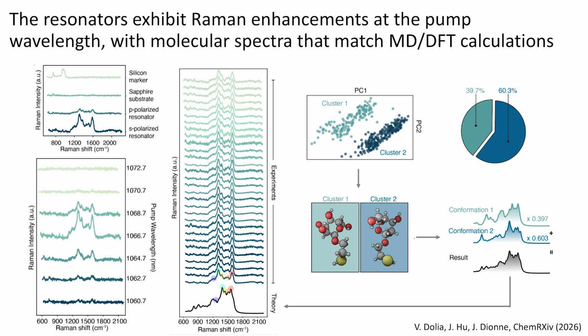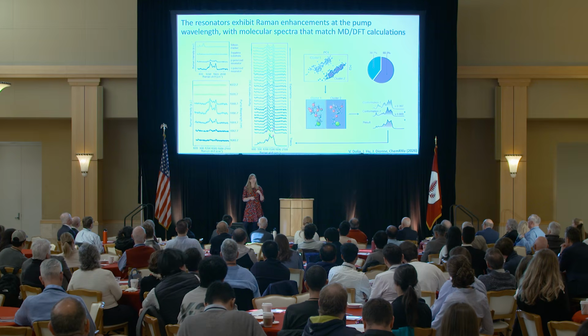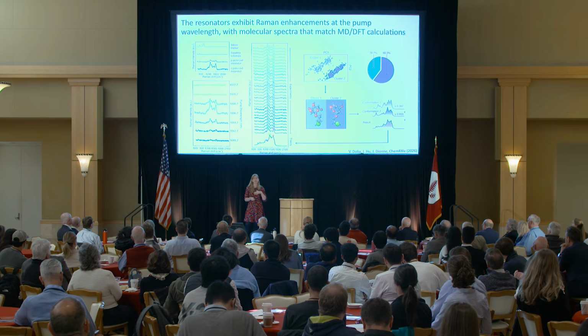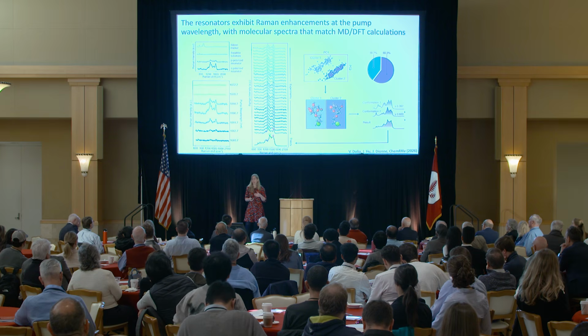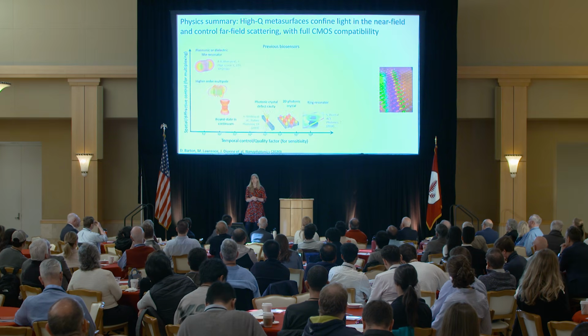And then, based on the Raman spectra and the amount of time that the molecule spends in different conformations, we're integrating for on the order of tens of milliseconds, up to about a second. We can take weighted averages of the Raman spectra based on how long it spends in those conformations and precisely get back the experimental Raman spectra that we measure. So this, for me, is pretty exciting because it means there's actually a path to get information not only about what molecules are there, but what their structure is, potentially in even a dynamic environment and with single molecule resolution.